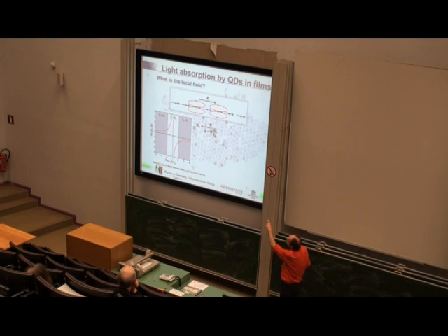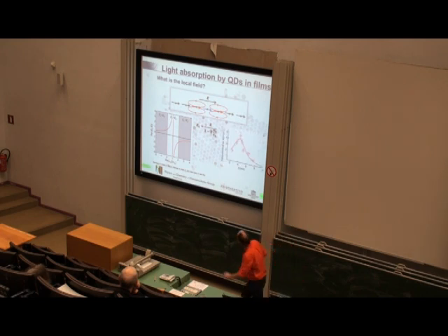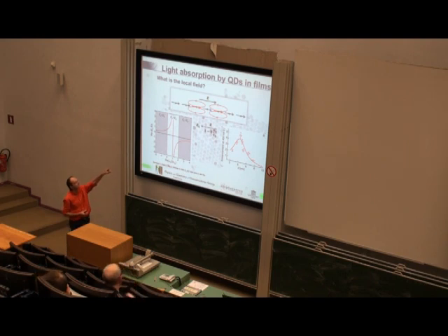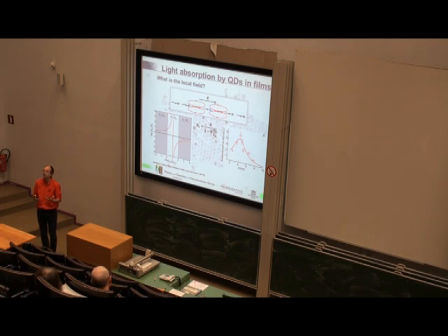you see that you will have a local field exceeding the applied field in a certain range of this alpha S over epsilon host term. And that's exactly what is happening here. We are working under conditions, sizes, combination of sizes of dots and packing of the dots that make this denominator smaller than 1. And so the local field is actually larger than the applied field. And these dots, they all help each other to absorb more light.